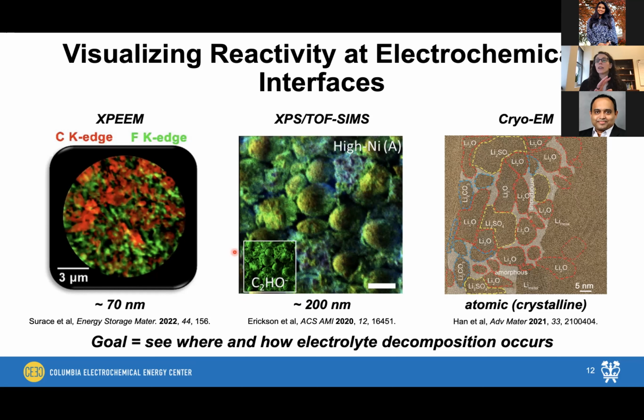Similarly, at the lab scale, you can also perform X-ray photoelectron spectroscopy imaging. You can also do TOF-SIMS, so mass spectrometry based techniques or XPS based techniques, to actually start to understand the chemical composition of what is deposited on your composite surface. At the lab scale, your spatial resolution here is going to be limited to about 200 nanometers. So a little bit less well resolved than the XPEEM approach, but still good enough to distinguish whether you have decomposition on your additives or your active particles here.